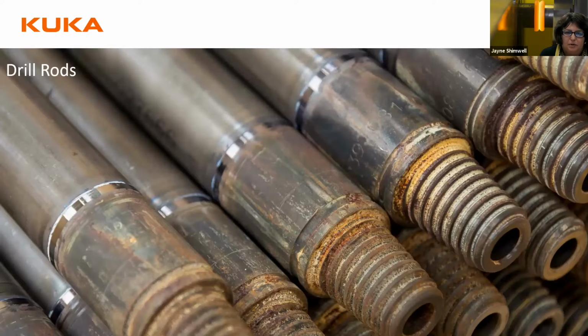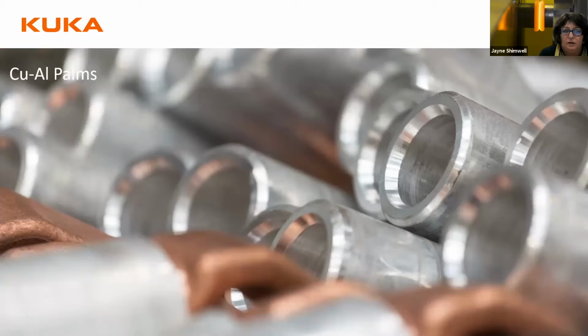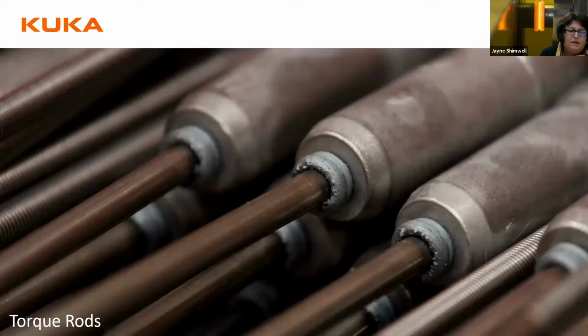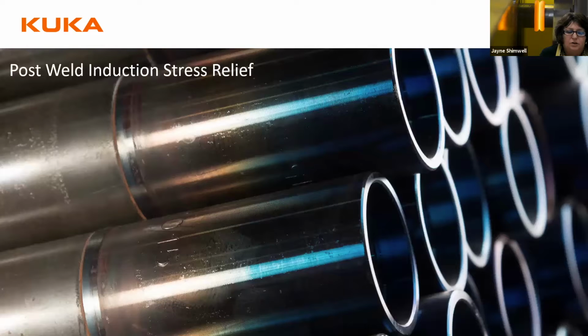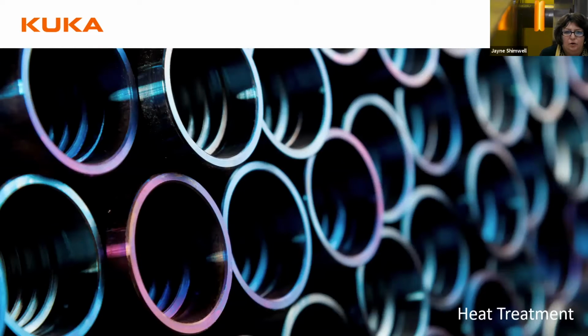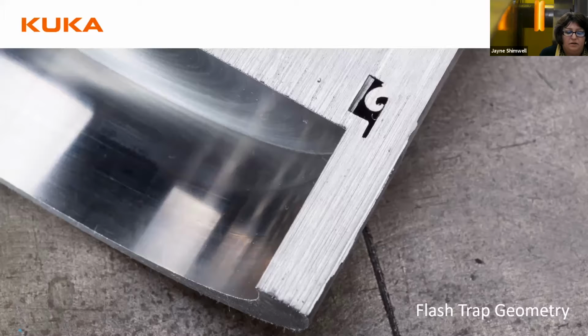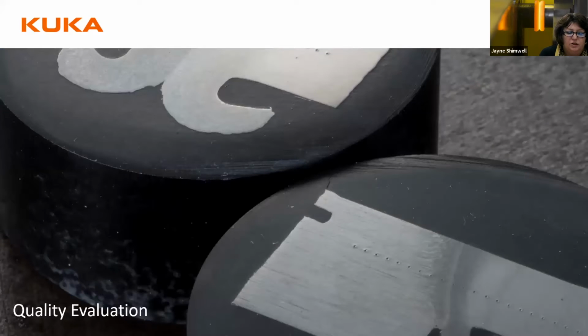And we have the largest subcontract department in the UK, with several machines ranging from 15 tons capacity up to 150 ton capacity. And just to give you an indication of what that means in terms of capability, for medium carbon steel, we can join components ranging from approximately 4 millimeters diameter up to 110 millimeters diameter solid, tubulars up to approximately 220 millimeters diameter with a 25 mil wall thickness. We also friction weld many bimetallics. The capability for those though is dependent upon geometry and also specific material combinations. Subject to component diameters, we can weld lengths up to 12 meters.